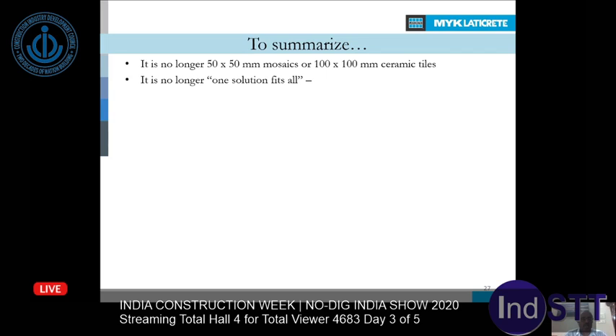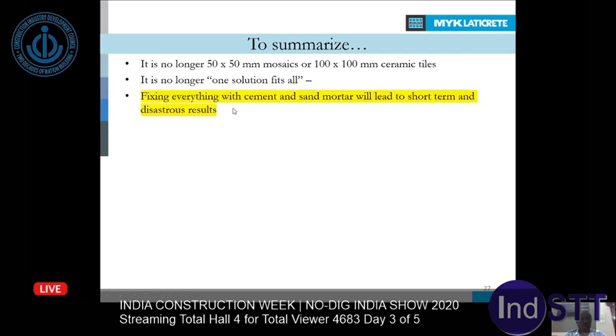So to summarize, as I said, it's no longer 50 by 50 mm mosaics or 100 by 100 ceramic tiles. The systems are changing, and nowadays you don't get less than probably 600 by 600 or more than that. And no longer is there one solution where you take sand, cement and fix everything. It is not possible. It's not going to give you the right material, right productivity, and a lot of issues come with that. As I said, fixing everything with cement, sand, mortar will lead to short-term and disastrous results.